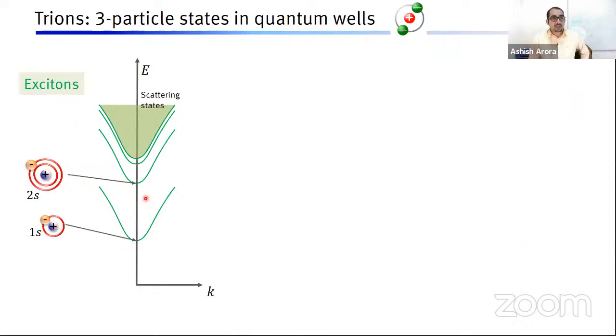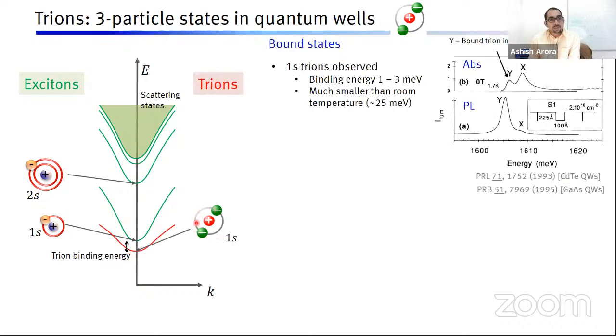Now we look at these excitons first. There are these ground and excited states of excitons and scattering states. If we add one more electron in this orbit of this exciton, then we get a trion. And this trion now starts to absorb below the exciton by an amount equal to the trion's binding energy.